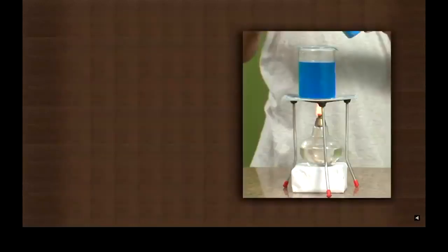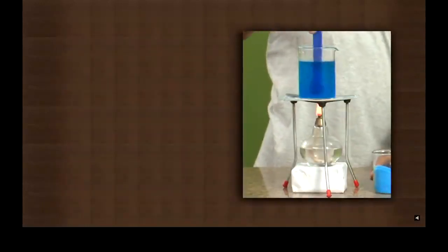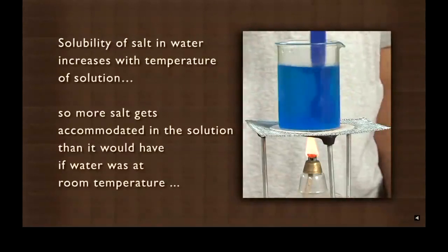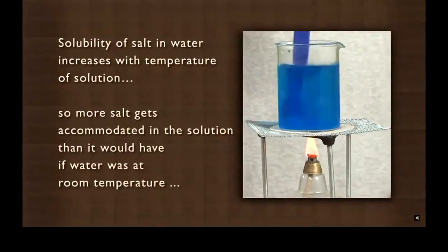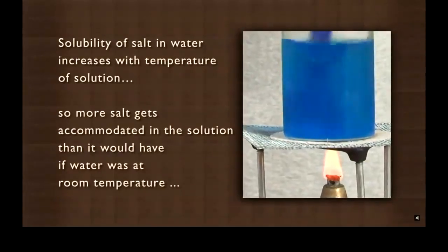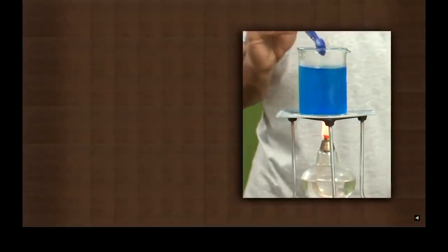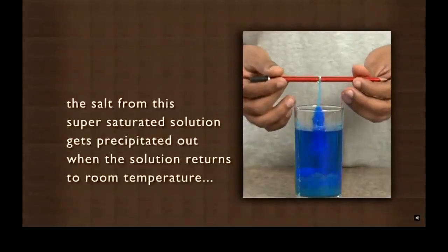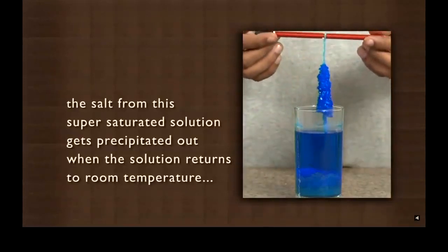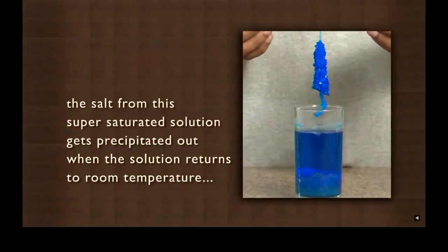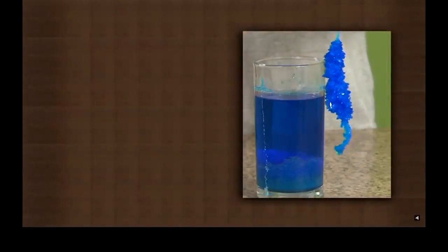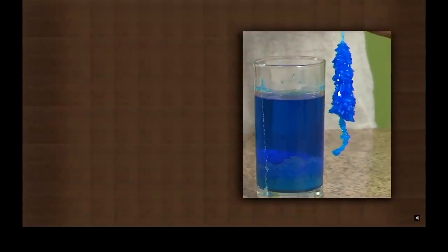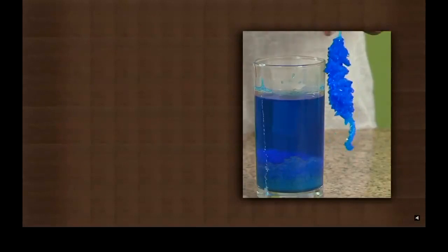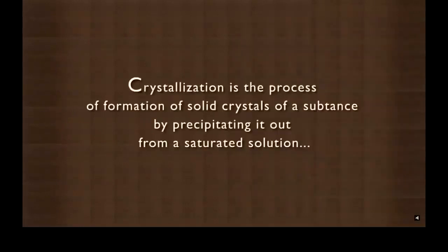This happens because the solubility of salt in water increases with temperature of solution. So more salt gets accommodated in the solution than it would have if water was at room temperature. This solution is called a supersaturated solution. The salt from this supersaturated solution gets precipitated out when the solution returns to room temperature. The salt molecules that get precipitated out start forming crystals at the nucleation center, which is the thread in this case. Crystallization is the process of formation of solid crystals of a substance in this case. Crystallization.